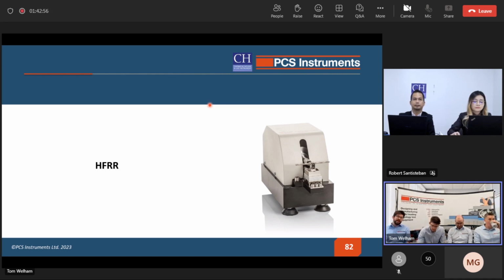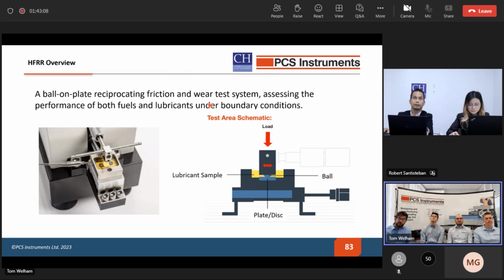So, the HFRR, like Robert said, most of you will probably be very familiar with this instrument. This is one of the first instruments developed by PCS. It's the high-frequency reciprocating rig, and it consists of a ball specimen, which is the upper specimen, and a disc. This ball is loaded against the disc and vibrated at a high frequency back and forth in a lubricant bath, and this simulates the performance of both fuels and lubricants under boundary conditions. The pot which holds the disc is heated and the temperature is monitored at all times, and we get a continuous friction measurement throughout the test.